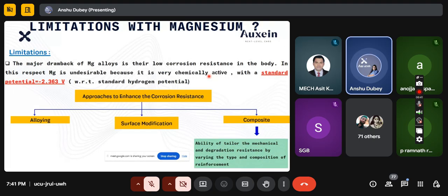But there we cannot use pure magnesium. Why? Because the standard electrode potential is minus 2.363 volt, which is very, very high if you compare with the standard hydrogen potential, which will lead to high degradation of magnesium. So that is also not our target, because we don't want things to degrade very fast. If the bone is not healed, then what is the point of having magnesium? So we should have such material which will degrade with the integration of the bone.